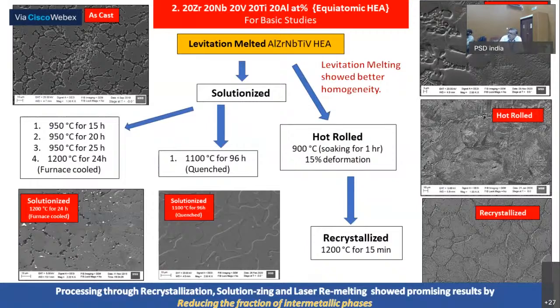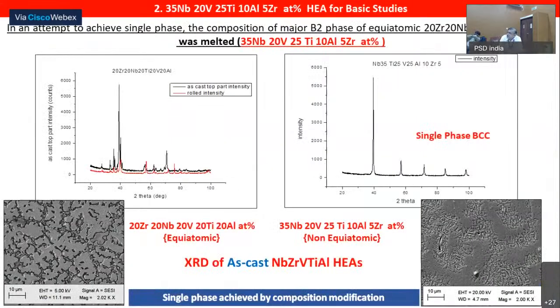This on the left side is the as-cast material, but when you do laser surface treatment on that, the same single phase grain boundary can be increased. You see it on the right top. Then we did levitation melting, rolling, crystallization, and solutionization, and in the process we end up with a single phase material by levitation melting, solutionizing, and then heating at 1100 degrees centigrade for 96 hours. So you do form the single phase material. This does show it, but it's a sluggish process. It also shows the structure is very, very stable.